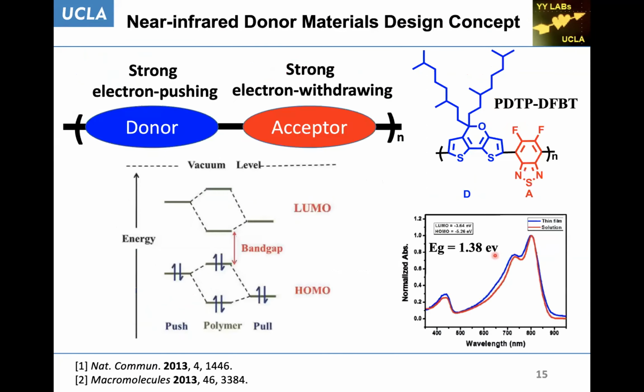So now I want to go a little bit into details about our research. The idea of designing the infrared polymer is this donor acceptor push and pull, electron pushing and withdrawing idea. You take these 2 molecules and fuse them together by synthetic chemistry. So the band gap becomes smaller. They adopt the LUMO level and HOMO level of the different materials. So this is the material that we collaborated on with Sumitomo Chemical.